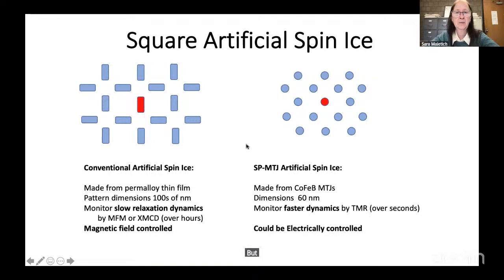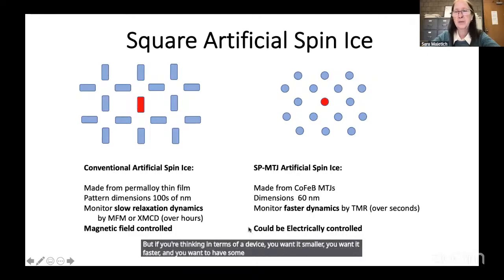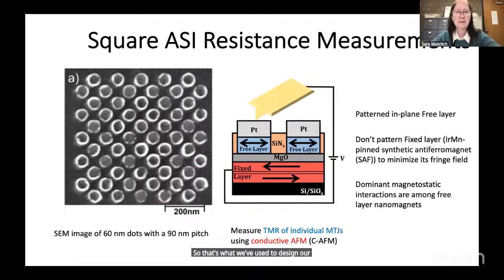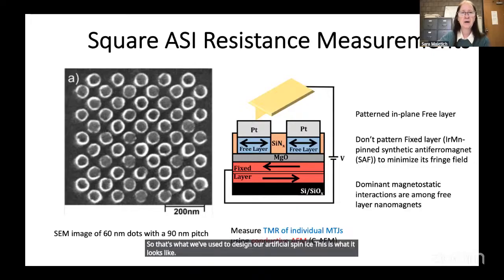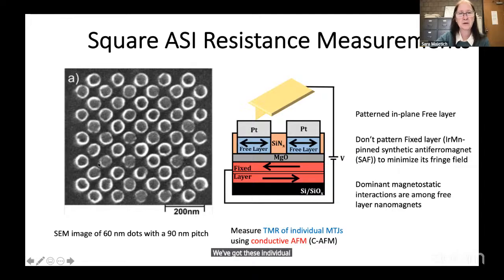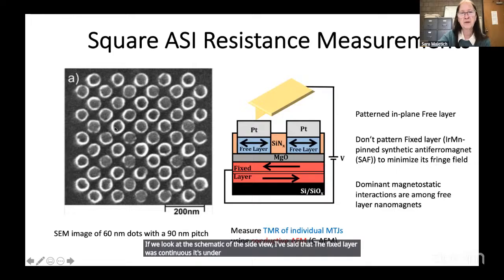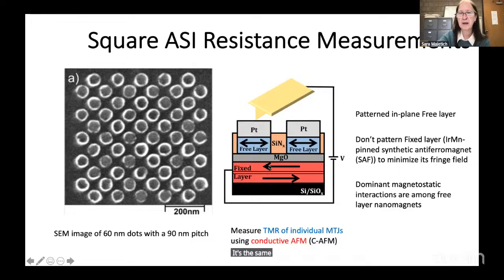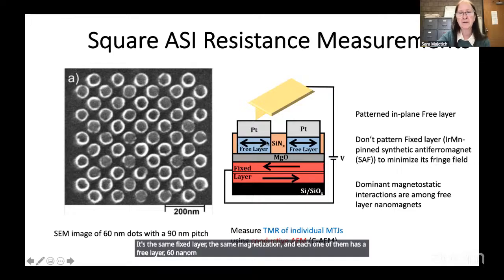But if you're thinking in terms of a device, you want it smaller, you want it faster, and you want to have some sort of electrical control of the inputs and outputs. So that's what we've used to design our artificial spin ice. This is what it looks like. We've got these individual pillars, but now they're closely spaced. And this is a top view SEM image. If we look at the schematic of the side view, I said that the fixed layer was continuous. It's under all of these dots. It's the same fixed layer, the same magnetization, and each one of them has a free layer, 60 nanometers in diameter, and the free layer of one could be a different direction than the free layer of another.